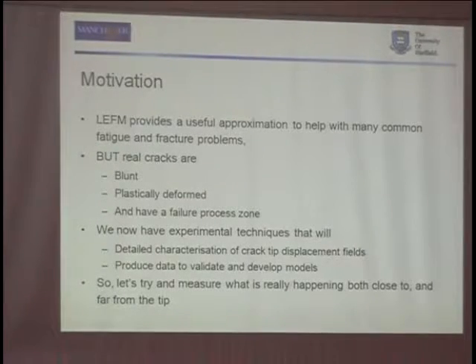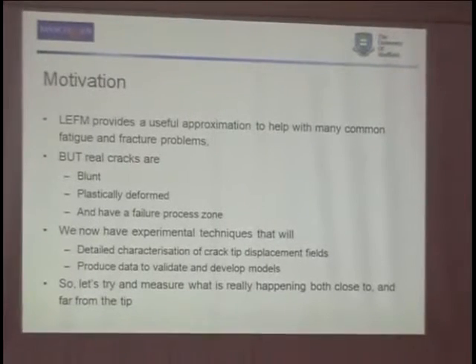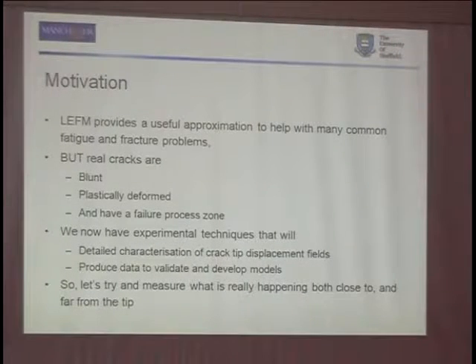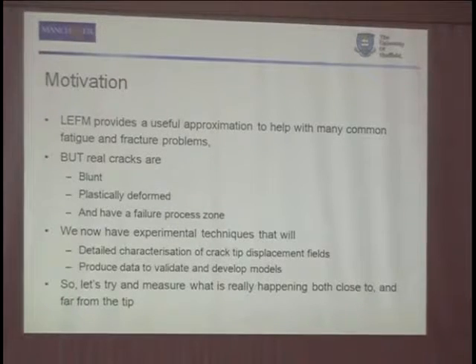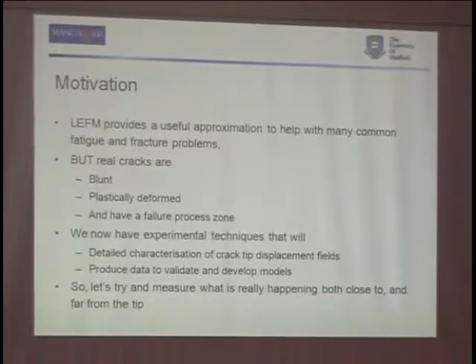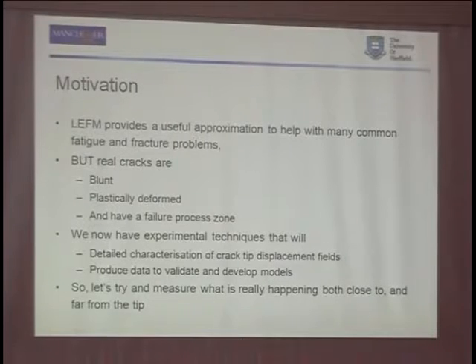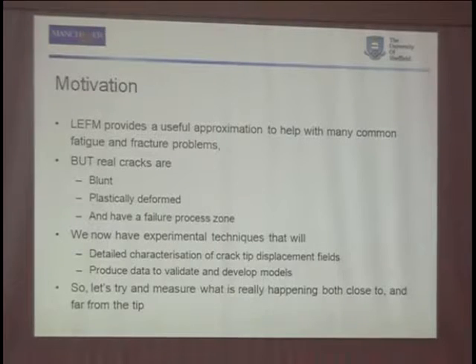The motivation behind this work is that we all agree that linear elastic fracture mechanics gives us a useful approximation to help with many fatigue and fracture problems. However, real cracks are blunt, they're plastically deformed, and depending on the loading and the material properties, have different failure process zones. But we now have many good techniques for detailed characterization of this crack tip field.